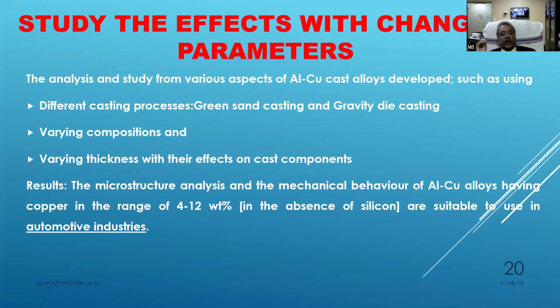Now what are the other parameters? We have worked in the green sand environment, with green sand casting and gravity die casting. We have changed the variation, and we also studied different section thicknesses, so the same casting having different cross sections. So what result is coming? The microstructure analysis and mechanical behavior show that aluminum copper alloys having copper in the range of 4 to 12%, in the absence of silicon, are suitable for automotive industries, because engine or engine related parts operate at temperatures of 150 to 250.